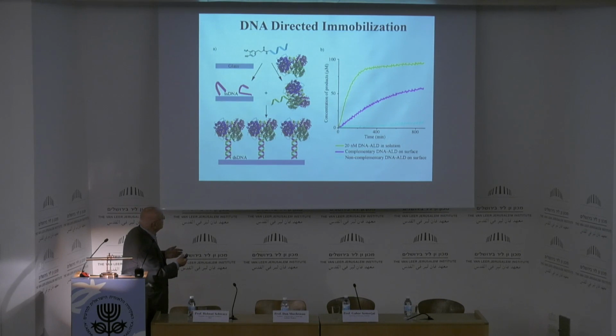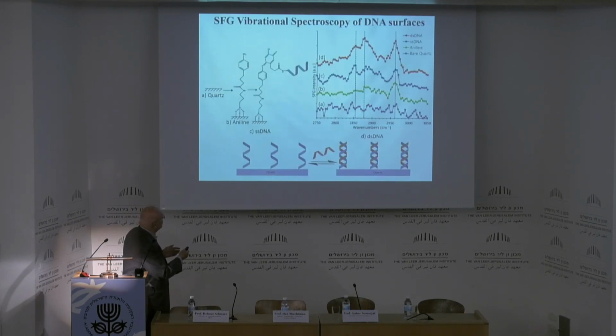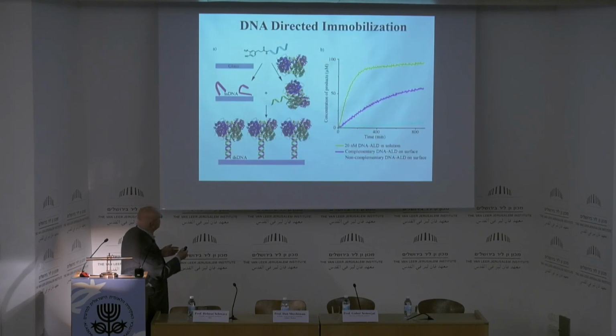So what we do is you take a strand of DNA and put it on a surface, which you can put a glue on it. The glue is an aniline glue on a quartz surface, and when you do that, you can take the enzyme and put it on the other strand of the DNA, and when you put the enzyme on the surface, you form the double helix here, and you have it anchored onto the surface.